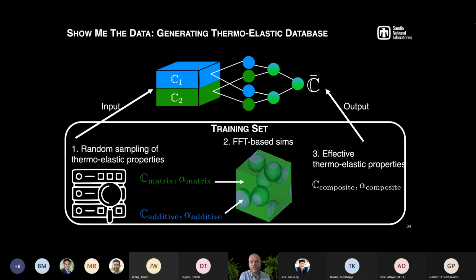Just to walk you through some of the steps, as I mentioned, we had to generate our training data on elastic data. In this case, I'm just going to give you an example of a very simple composite, but you can randomly sample properties for the matrix and your inclusions. We're collaborating with my colleague at Los Alamos, Ricardo Lebensohn, using his FFT-based simulations to rapidly predict the effective elastic properties of these composites, and then using that information to train our network.